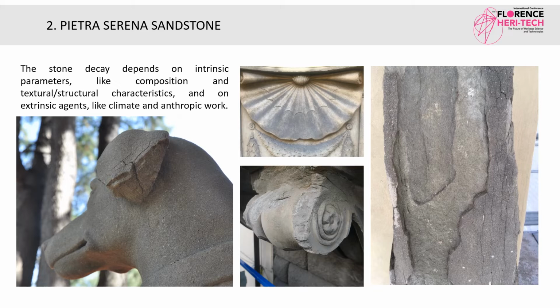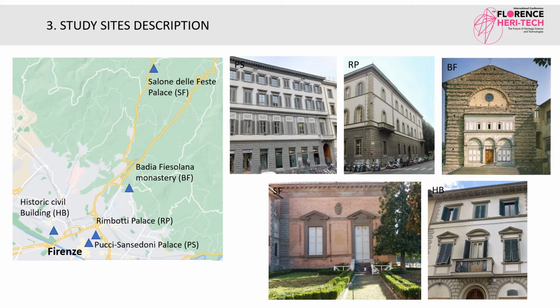Another decay phenomenon is always due to water absorption, which involves a decrease in the characteristics of the original stone and a significant increase in the initial porosity. The sudden change in temperature leads to cracking and weakening of the areas. Property changes of the material produced by decay, as for corbels, make the material less suitable to perform the structural function over time. Analysis on Pietra Serena corbels from 5 Florentine buildings was performed to implement the investigation protocol